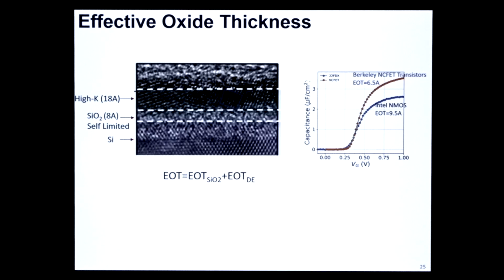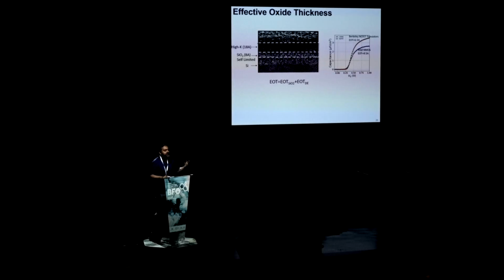In semiconductor literature, capacitance is often explained or quantified with a parameter called effective oxide thickness. It's nothing but the inverse of the capacitance normalized to silicon dioxide's capacitance. So if your effective oxide thickness is larger, then your capacitance is lower. If your capacitance is higher, EOT, effective oxide thickness, is lower. Usually what we have is silicon, then an 8 angstrom SiO2 in our advanced transistors, the transistors that you are using in your computers. And then, as I said, we usually have a 1.8 nanometer hafnium dioxide. So typically what we get is an EOT of 8 angstrom from SiO2 plus something from the dielectric.